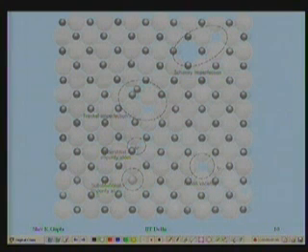If I have FeO, iron oxide, where all the iron ions are supposed to have double valence, valency 2 plus. But if say I have two ions introduced which have valency 3, to make it electrically neutral, one of the bivalent ions should be missing from its location.